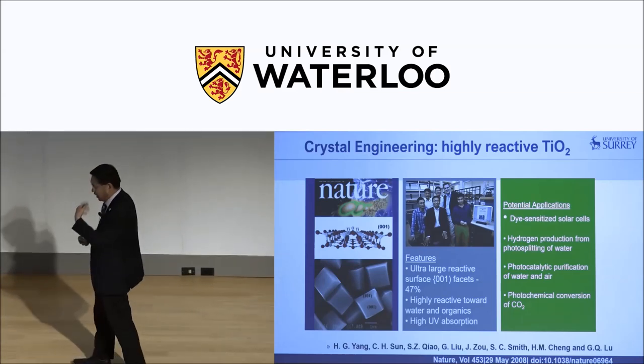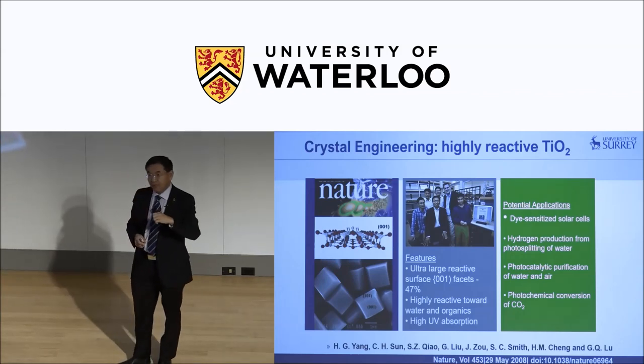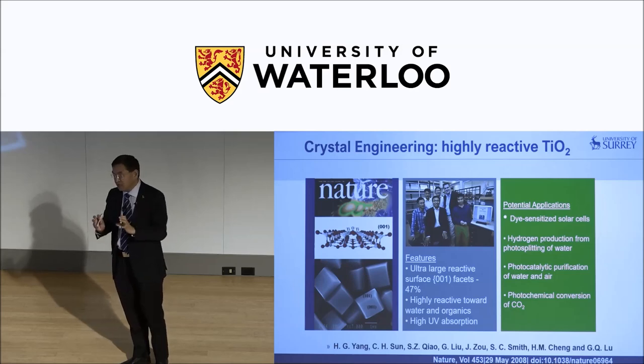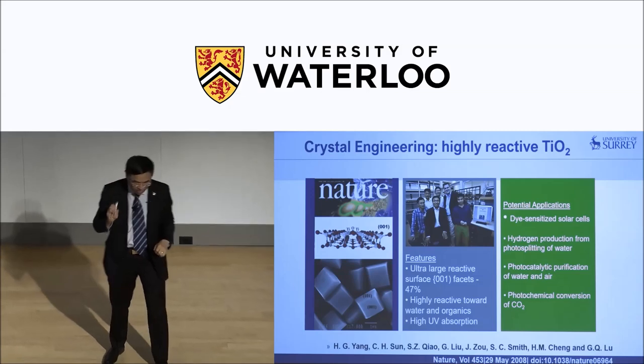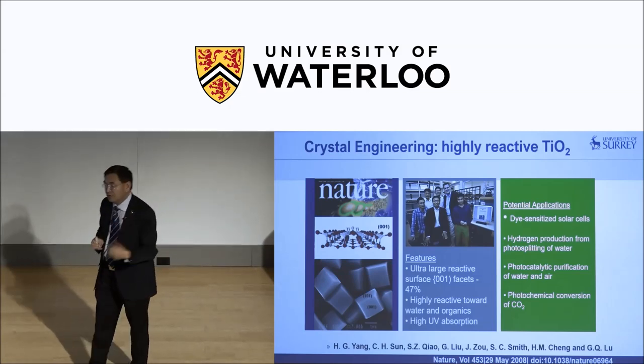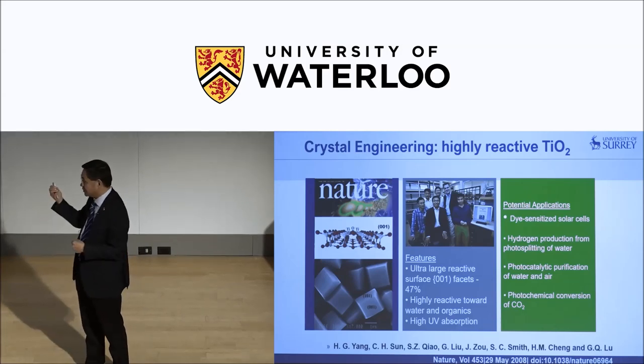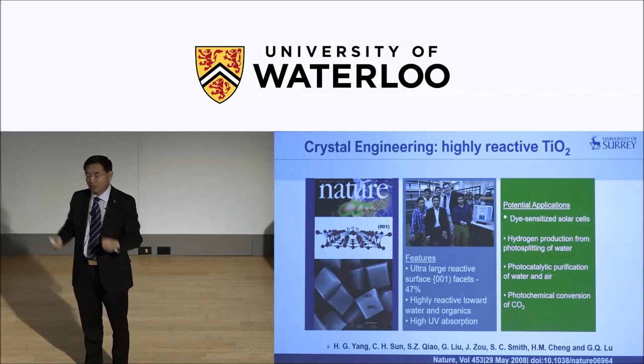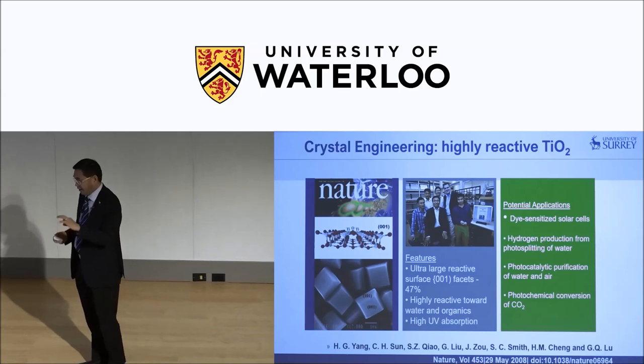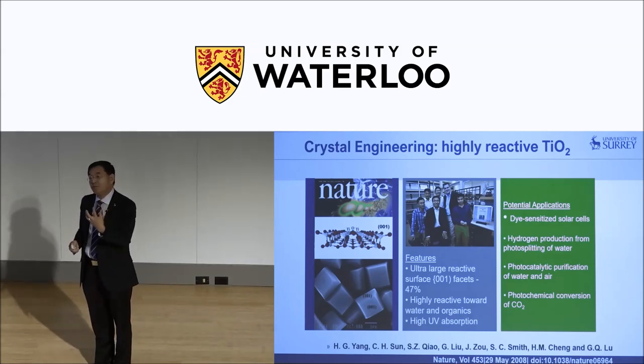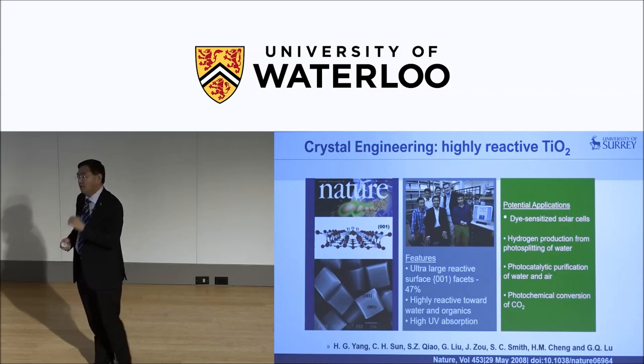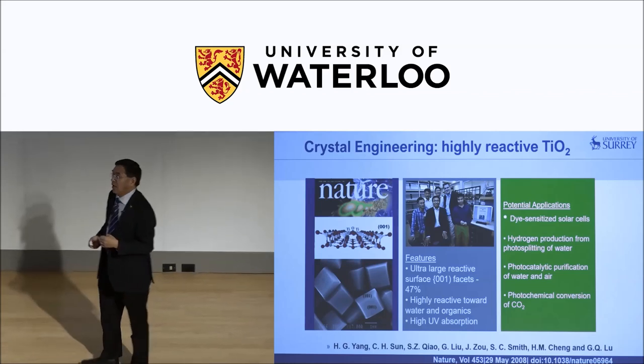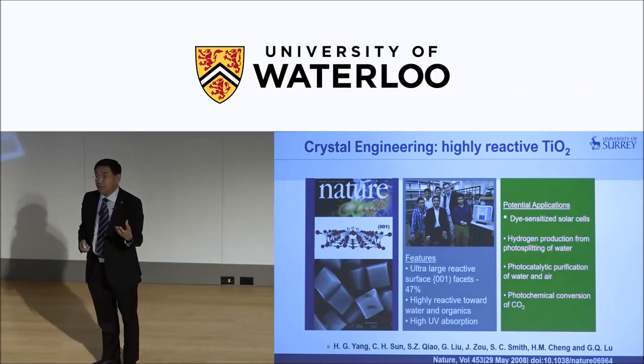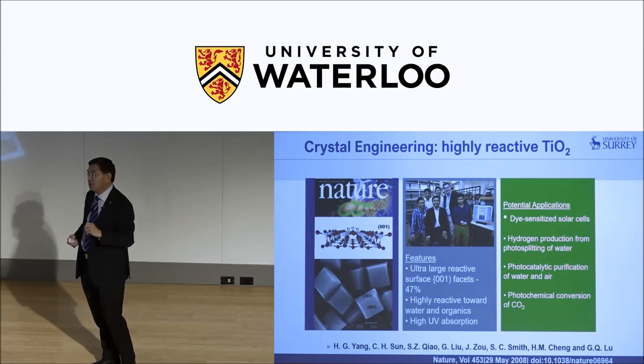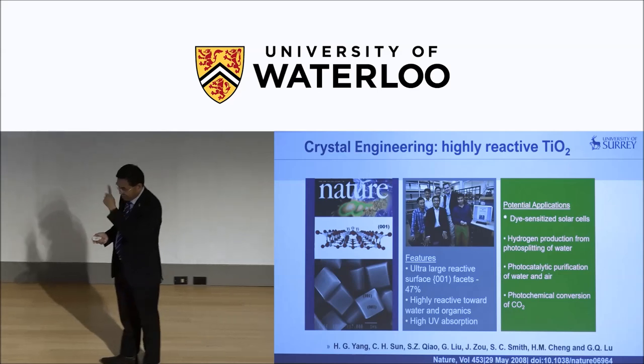And this is a very simple hydrothermal, but with a lot of theoretical calculation, you find out, okay, for titania, it does exist in different phases. Okay, so titania anatase crystals, typically you can synthesize by hydrolysis or flame temperature reaction to synthesize titania very easily from the salt of titanium. And you can achieve basically 95% of the stable phase, which is the 101 facet in the crystallography terms. And the 001 facet is the most reactive because it's unsaturated 5 and 6 coordinate titanium oxygen bridges. So therefore, we designed this, and I'll show you the next slides.